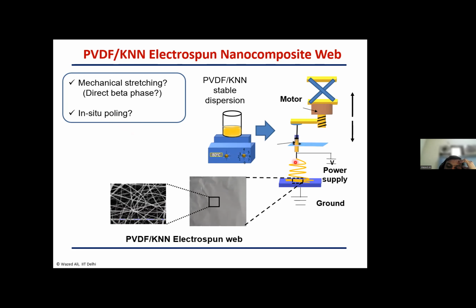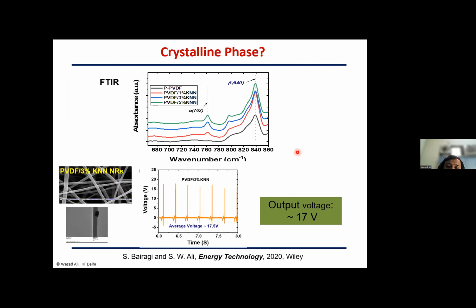In this case, the stretching is happening on the polymeric part. So more and more stretching means more and more alpha is going to convert into beta from the PVDF part. And at the same time, the dipole is going to be oriented by application of the high voltage. So in this electrospun fiber structure, we got 17 volt output voltage, right? 17 volt output voltage as compared to the film. Film actually, as I mentioned, 5 to 6 volts. But if you talk about this nanofiber structure, we got 17 volt output voltage.